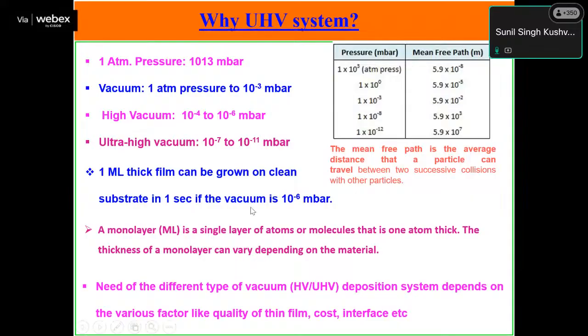Another reason is that when you have a very clean surface, one monolayer thick film can be grown inside the chamber in 1 second if the vacuum is at 10 to the minus 6 millibar. So it means if you have an ultra high vacuum system, once you put the substrate in, you still have a few hours to process, and there is no other growth on your substrate. That's the reason your interface will be of very high quality, and there will be no other contamination on your growing substrates. So I tried to highlight why we need the UHV system when we are talking about MBE and other growth processes.